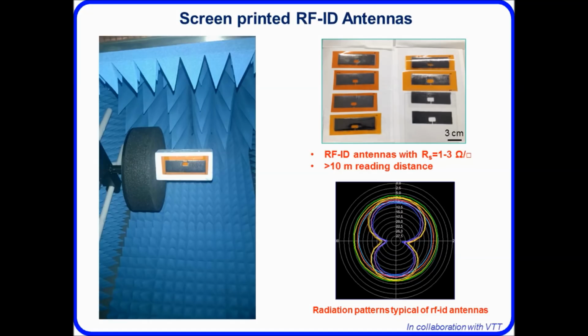But then beyond that, we now target radio frequency tags. So here we're looking at competing with typical silver and aluminium based metal antennas. So graphene again has some potential environmental implications. We can recycle these materials, but also we can attach other kinds of sensors to the graphene, or use the graphene antenna itself as a sensing platform, for example monitoring humidity or temperature. So these antennas now have a reading range of beyond 10 meters, which compares to typical state-of-the-art metal-based antennas.